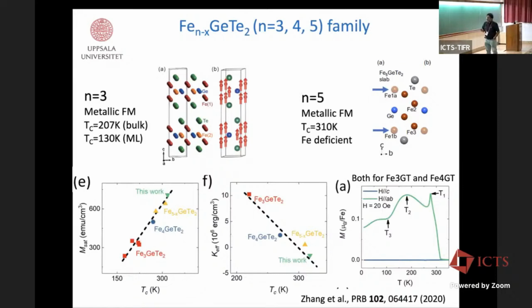In this paper, they have summarized the results for Fe3, Fe4, and Fe5. This is the saturation magnetization versus Tc. So obviously the saturation magnetization increases, and Tc increases when you increase the concentration of iron. The magnetic anisotropy parameter decreases, which is also understood when it becomes thinner. It has the highest value, then it decreases. What is intriguing is actually the magnetization versus temperature plot, which is, sorry, this should be Fe4 and Fe5, not Fe3.